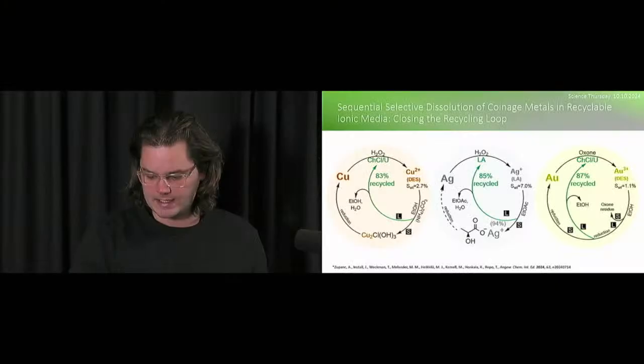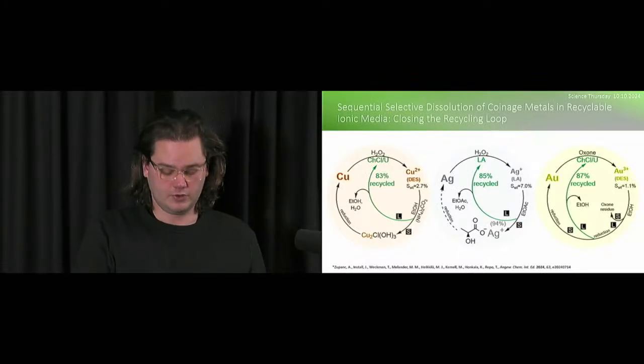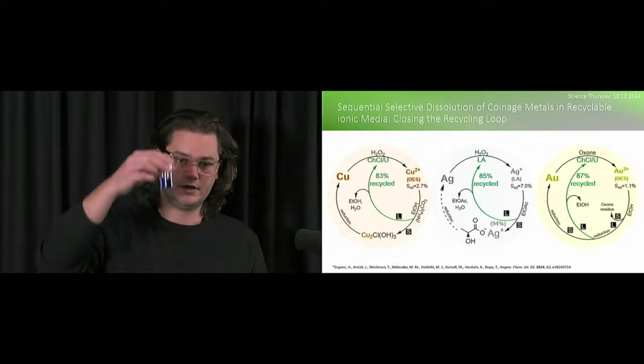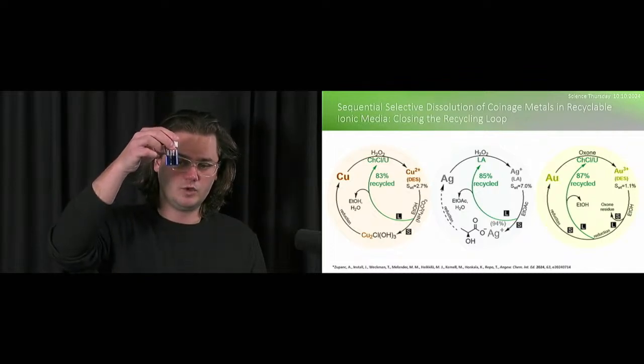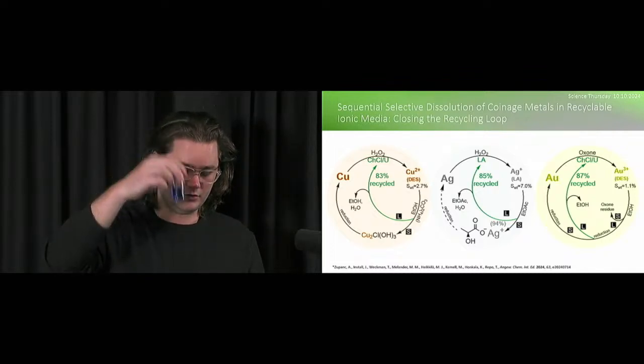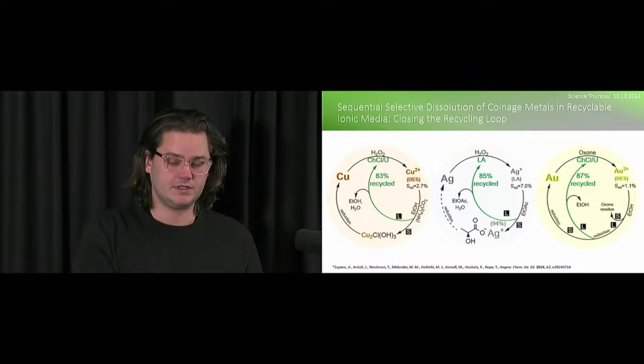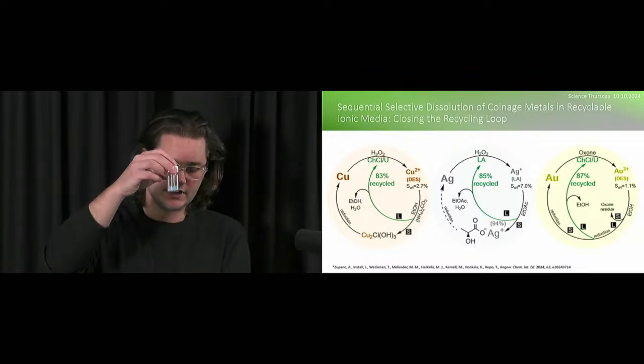So as I said before, I can maybe even show you again this slide. After this copper is dissolved, we put there ethanol and ammonium carbonate, and we precipitate out this copper chloride hydroxide. You can again see that this is a very nice blue color, which is a very well-known thing for the copper 2+ ions.